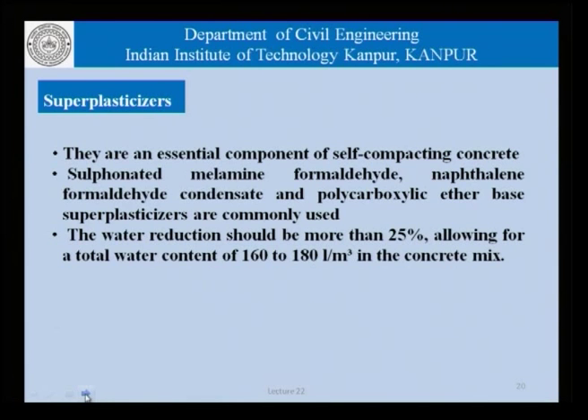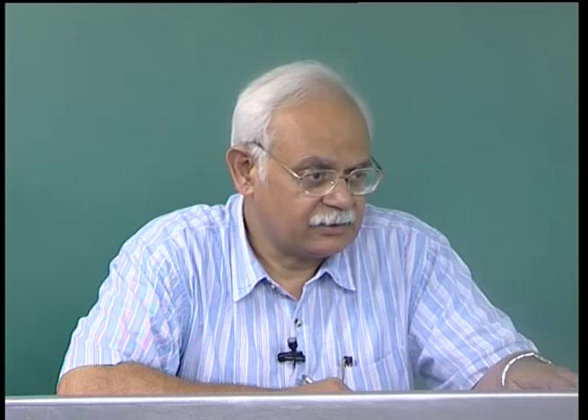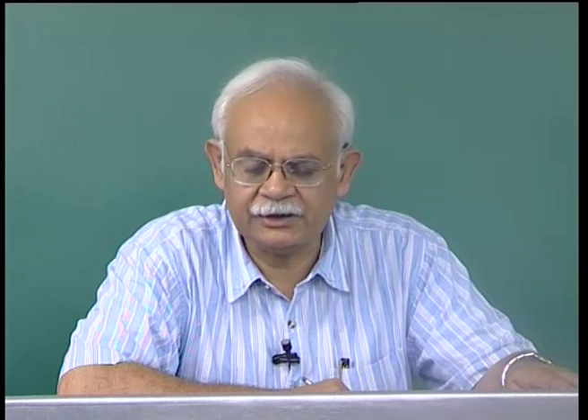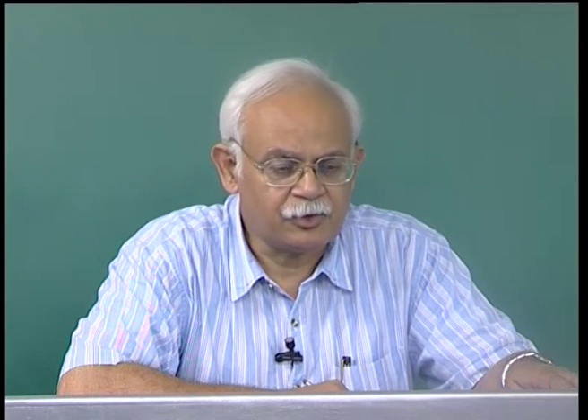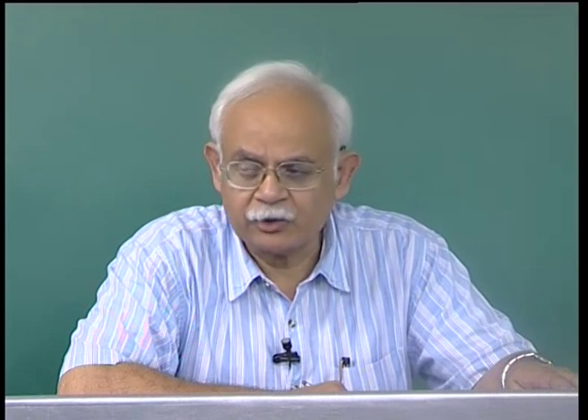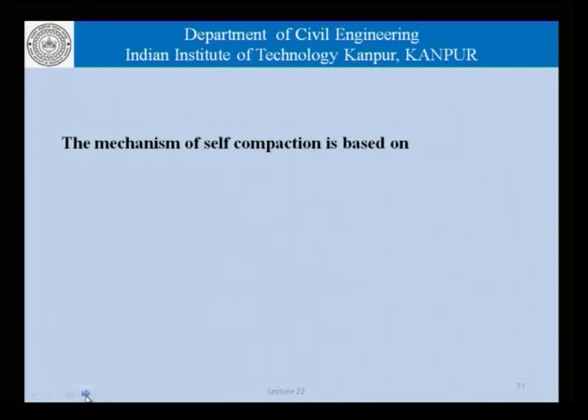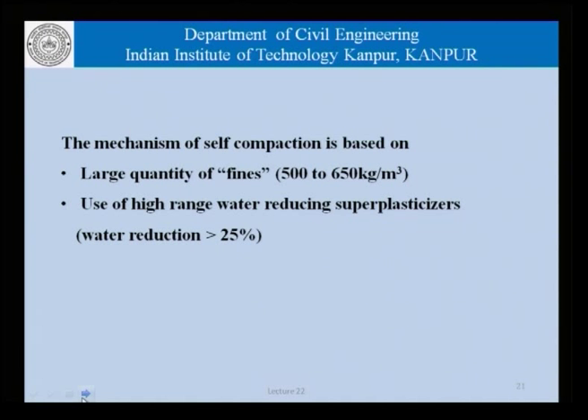As far as these admixtures are concerned, the water reduction achieved should be about 25% or more, so that the total content of water is restricted to about 160 to 180 liters per cubic meter. Anything more than that would make the demand on the powder content simply too high. Now, the mechanism of self-compaction in self-consolidating concrete is based on the large quantity of fines of the order of about 500 to 650 kgs a cubic meter, the use of high-range water reducing superplasticizers in the range of more than 25% of water reduction, and viscosity modifying admixtures. So, it is these three principal factors, or a combination of these factors, which helps us obtain self-compactability in concrete.